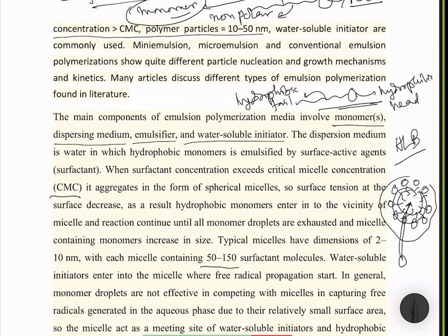The non-ionic surfactants are mostly referred to as protective colloids, which means that in emulsion polymerization they stabilize the final product more effectively. That is, when the polymerization is over, the dispersion of the polymer latex is stabilized by this non-ionic surfactant. So you have to use an ionic surfactant for the polymerization stage and a non-ionic surfactant to stabilize the product.